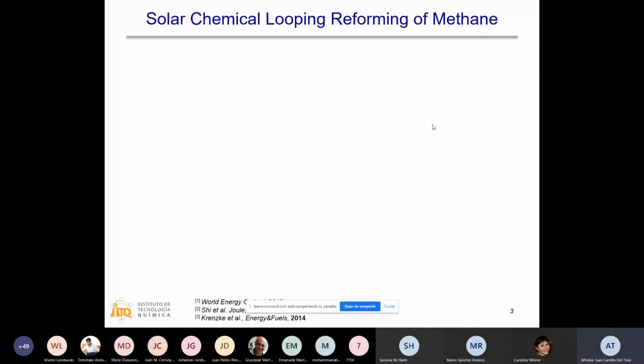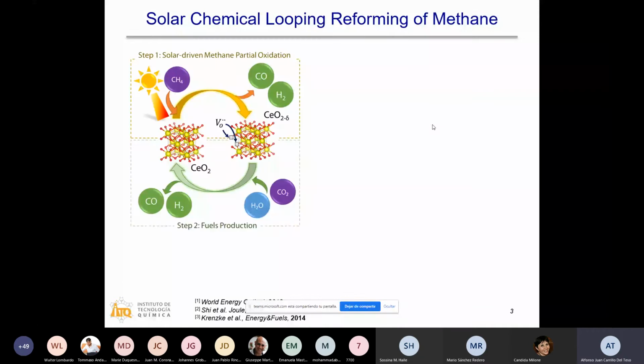So as a nice follow-up to the previous talks by Professor Jalí and Mario Sanchez, I'm going to show this two-step thermochemical cycling. However, here the difference is in the reduction reaction. Here I'm going to use methane as a reduction agent, and therefore in the first step we will have what I call the solar-driven methane partial oxidation. We will reduce ceria as our redox material, and we will create oxygen vacancies on the material, but we will also produce syngas in this first step of the thermochemical cycling. In the second step, we will inject CO2 and water into the reactor. Our reduced oxide will uptake oxygen from these two molecules, and we will also produce syngas.